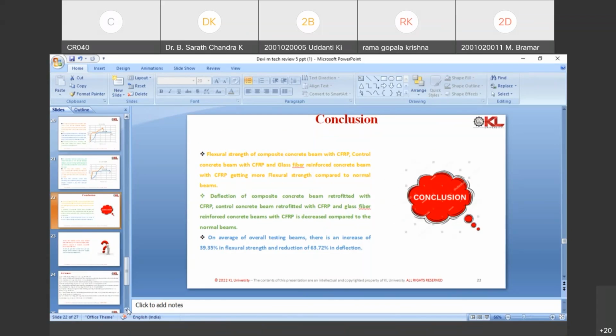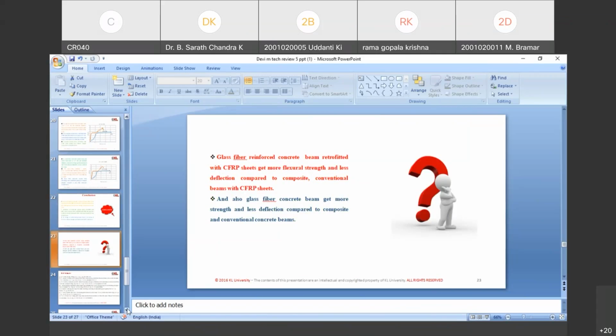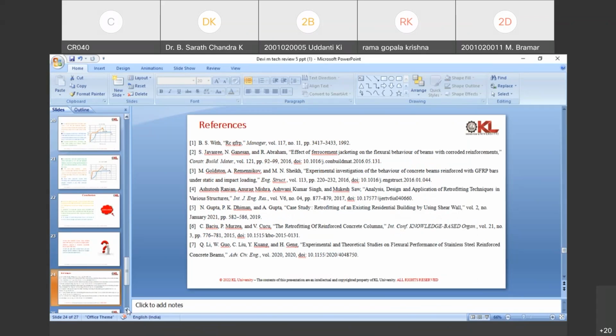On average, over all testing beams, there is an increase of 39.35% in the flexural strength and a decrease of 63.72% in deflection. The glass fiber reinforced concrete beam retrofitted with CFRP sheet gets more flexural strength and less deflection compared to the composite and conventional beams with CFRP. Also the glass fiber concrete beam gets more strength and less deflection compared to the composite and conventional concrete beams. Now these are my references.